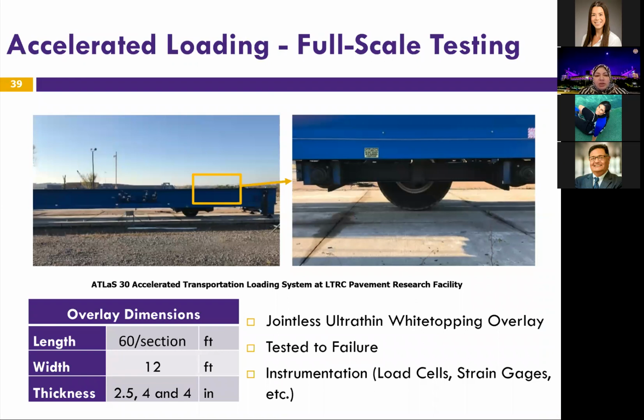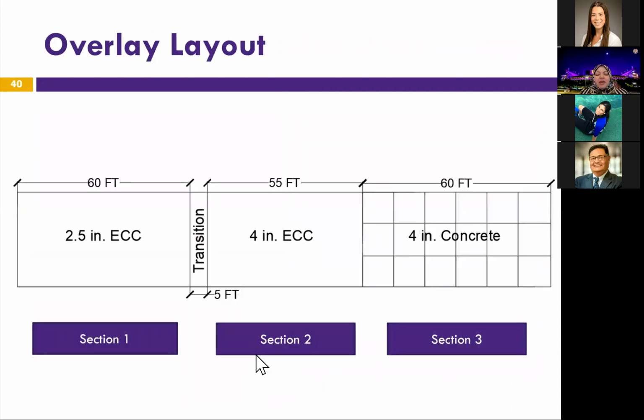We had a project where we wanted to do a full-scale testing in an accelerated loading facility. So we built an ECC pavement in the Louisiana Transportation Research Center Pavement Research Facility. And you can see this is the loading wheel right here. It's an ultra thin white topping over an asphalt pavement. And we have 3 sections, a 2.5-inch thick ECC, a 4-inch thick ECC, and a 4-inch concrete that's going to be used as control.